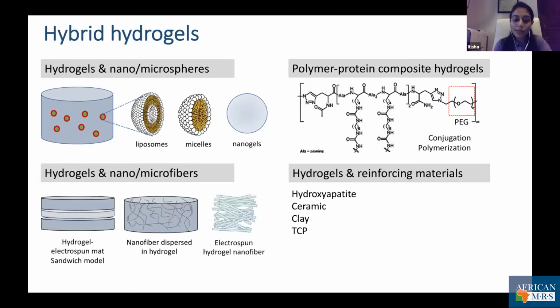So these allow for controlled delivery of therapeutic drugs or bioactive molecules, and also by incorporating the molecules into micelles or liposomes, it increases the loading efficiency of hydrophobic molecules. So it increases the loading efficiency within the hydrophilic hydrogel structure.